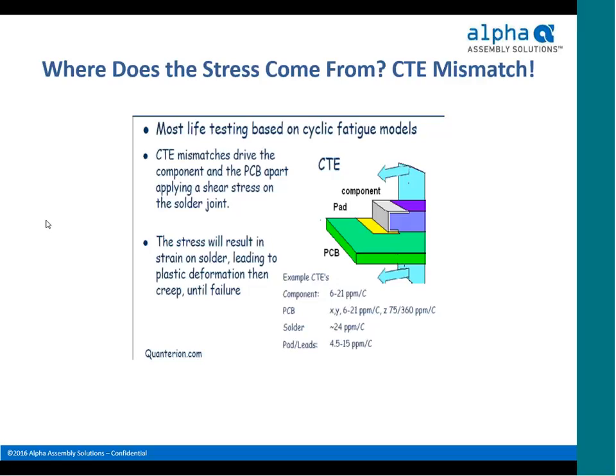The FR4, the copper for the laminate, the ceramic from the chip resistor, the plastic molding from the quad flat pack, the FR4 base and the injection molding on top of an FR4 base BGA package. All of these are going to have different thermal expansion coefficients. So as the temperature changes, each of these expands and contracts at different rates, and that puts stress on the one thing holding it all together, which happens to be the solder joints.